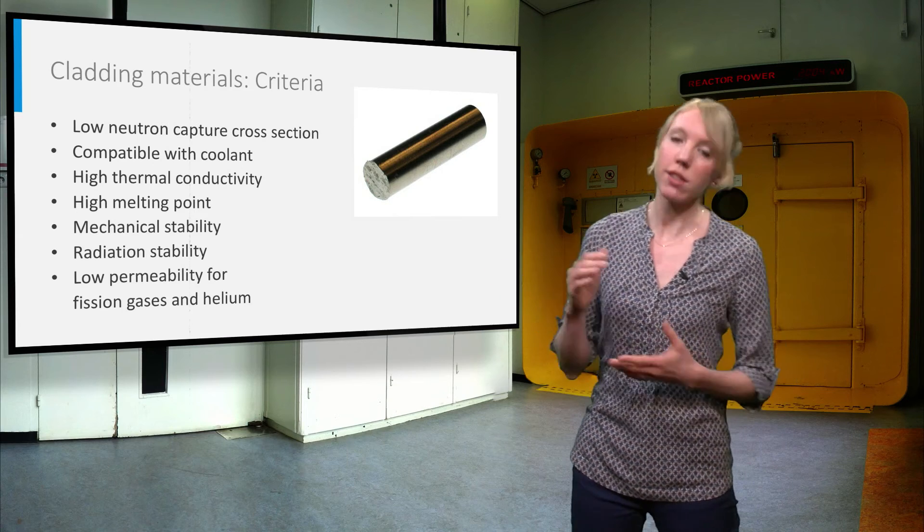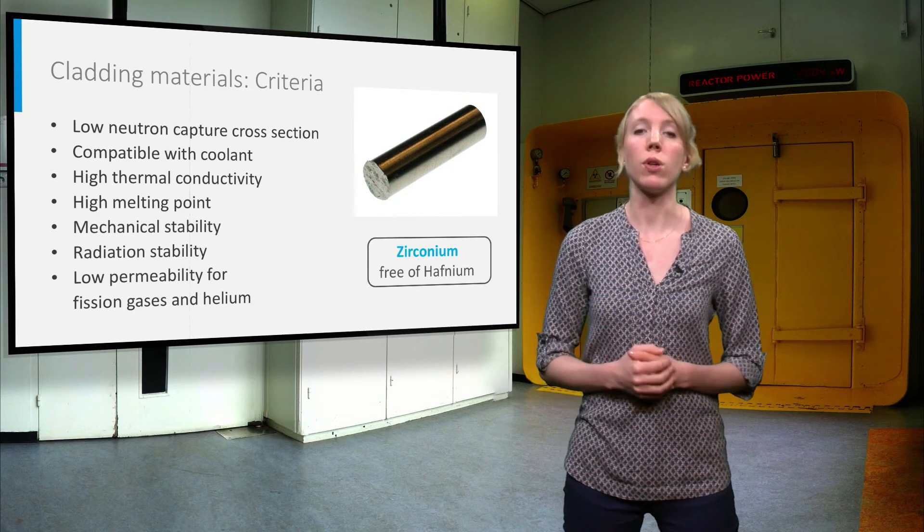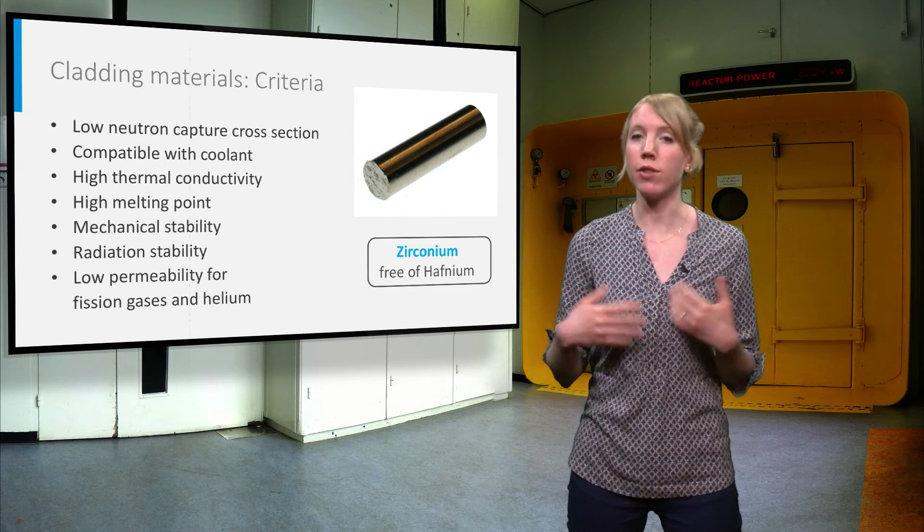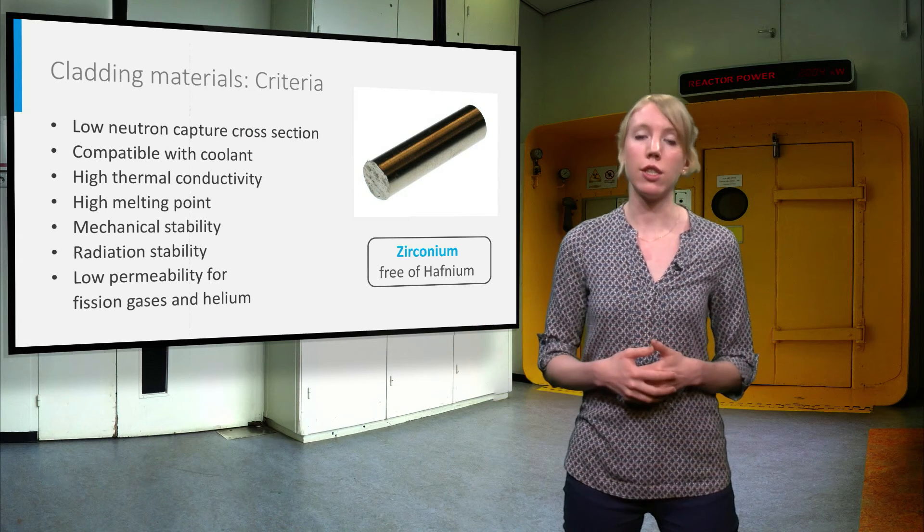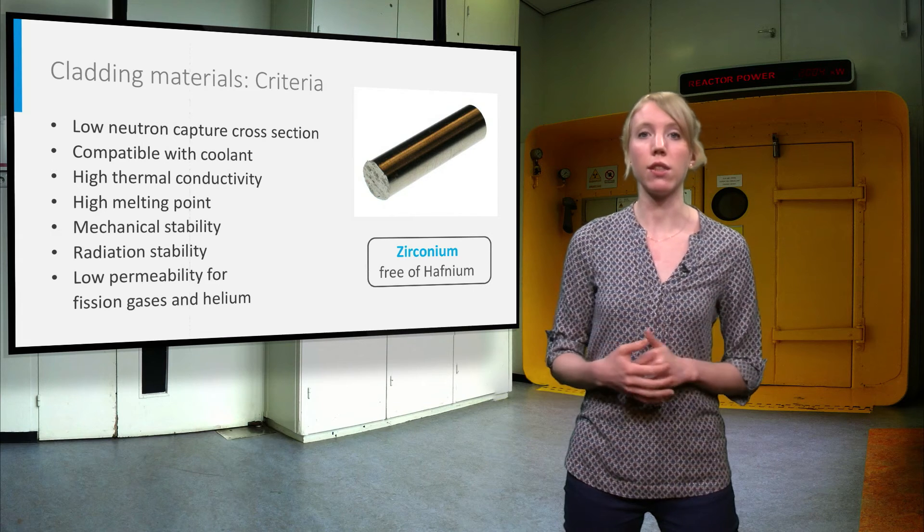In practice, only a limited number of elements fulfill this criteria. Zirconium was historically chosen as an advantageous material. However, this needs to be a special grade of zirconium with a very low content of hafnium.